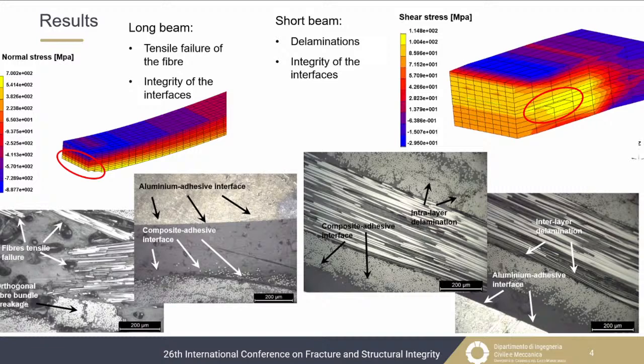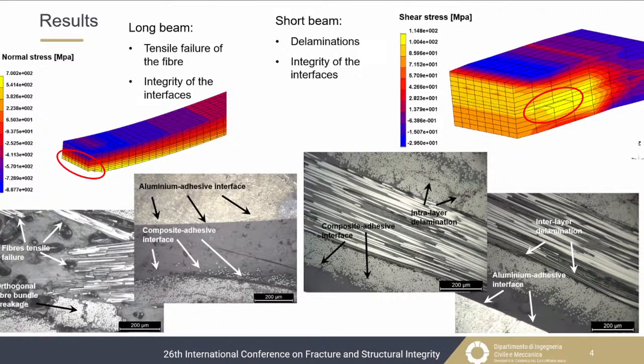Yes, this is a preliminary simulation, so we have used this simple geometry, but I can expect more or less similar behavior also for bigger geometry. Usually these materials are used for panels, so I can expect delamination, as in the case of the short beam, if the stress scheme is similar to that of the short beam, or I can expect also a failure of the fiber on which a tensile stress is acting. Usually, I think these are the two main modes of failure.